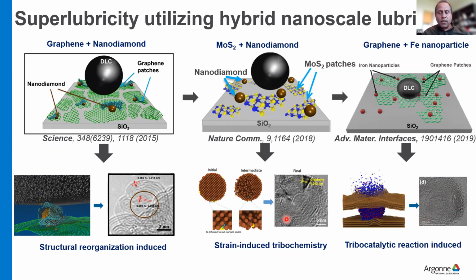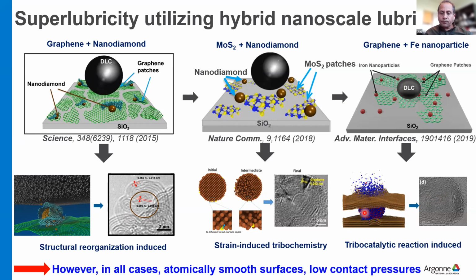So in all these cases, the end product is very similar: formation of these nice, beautiful spherical carbon nanoparticles that reduces the contact area and gives rise to the superlubricity. Now, in all these cases, we always used atomically smooth surfaces and low contact pressures, but for practical application, we really wanted to see how it works on rough surfaces at high contact pressure and high sliding velocities and speeds.